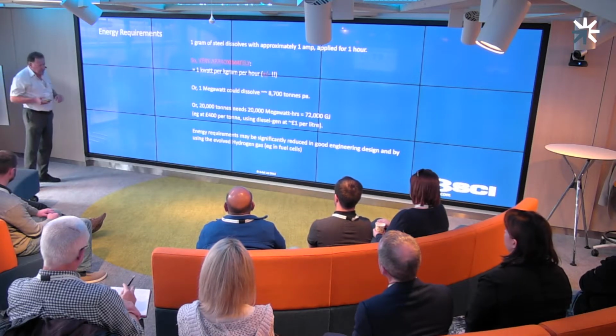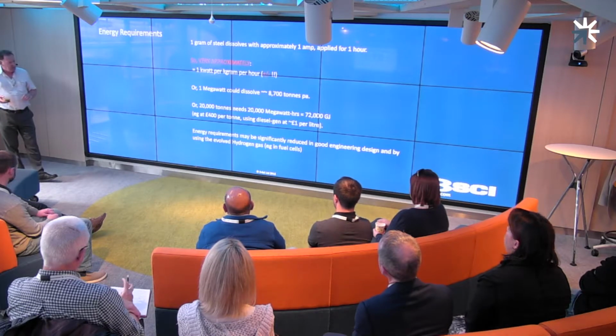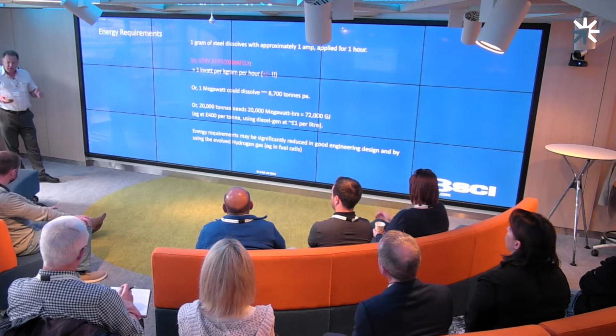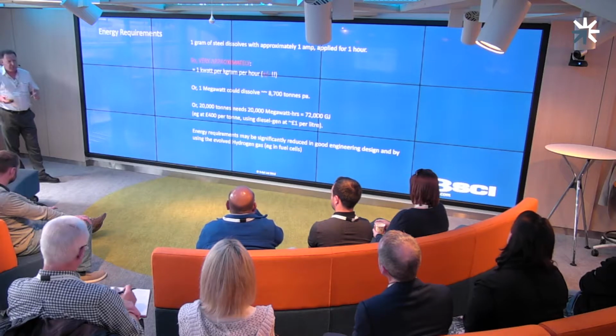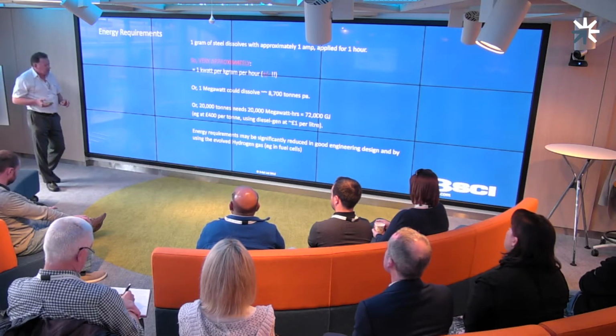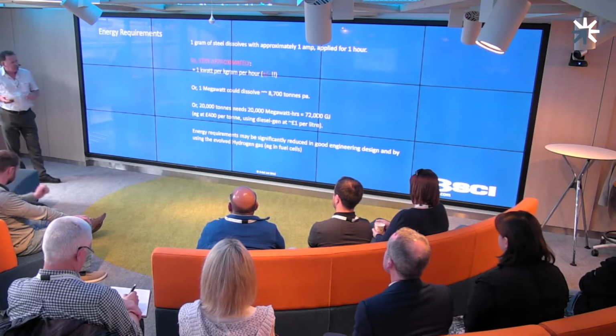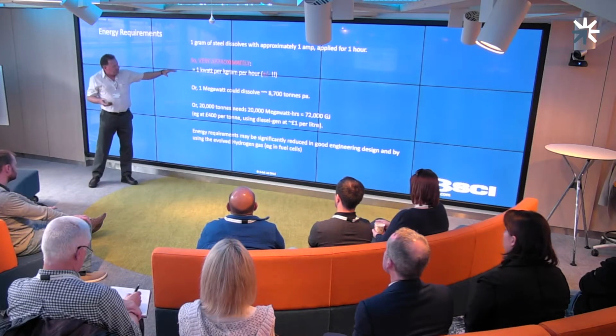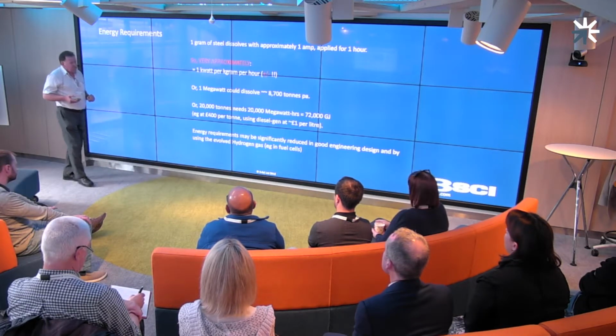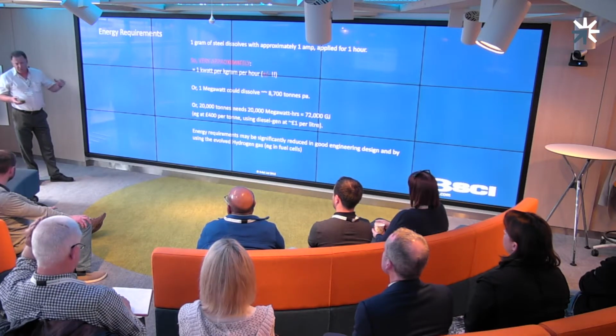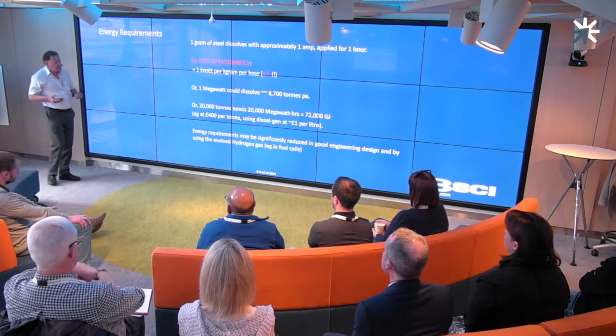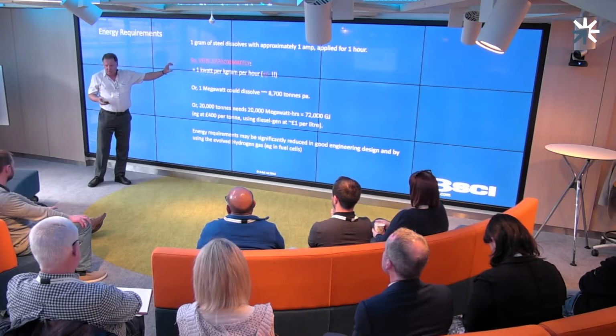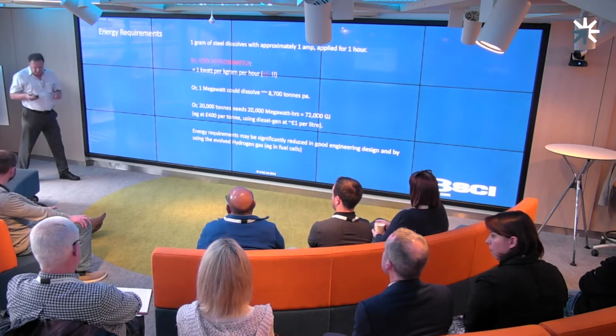One of the issues which I raised earlier on is the available energy in the hydrogen gas. And we haven't looked yet at the possibility of how we collect the hydrogen gas. Clearly it's a question of just capturing it. When you look at the electrochemistry involved here, for every atom of iron which you're dissolving, you're producing an atom of hydrogen. So there are some significant quantities of hydrogen being produced that we should be able to capture and reuse as an energy source to contribute towards this process. So this estimation at the moment that we will be roughly in this ballpark of a kilowatt per kilogram per hour, that may even now be pessimistic. And with the efficient use of hydrogen, we may be able to get this down to hundreds of watts to achieve a kilogram per hour of dissolution of the steel structure.